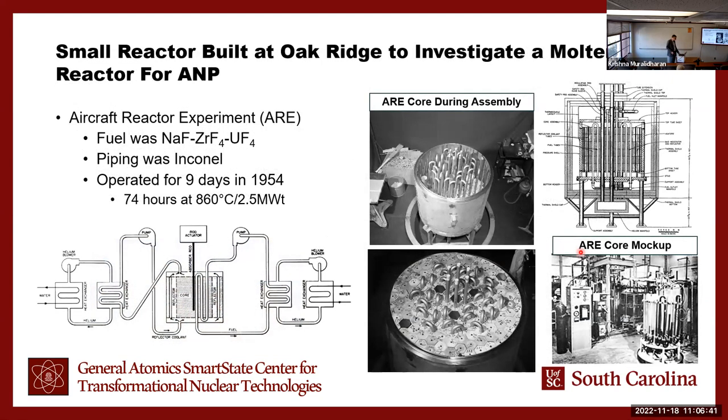So at Oak Ridge National Lab, they built a small reactor to investigate the possibility of running an airplane with a reactor. Fuel was sodium fluoride, zirconium fluoride, uranium fluoride as a liquid. And here you can see the small reactor under construction. Here's the top finished, sort of a schematic. Here's the mock-up flow diagram. And the heat at that point we would just dissipate, because it's just a demonstration. And the thing worked, ran for 9 days on and off, got about 74 hours at 860 centigrade, generated 2.5 megawatts thermal.